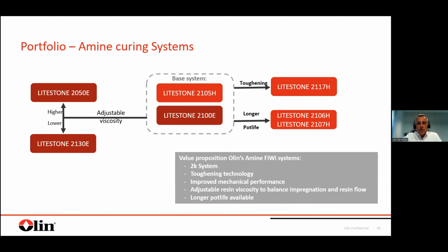For the amine, our portfolio looks similar. Again, we have kind of a base system, which is always a good starting point if somebody starts working on filament winding. Then we have a hardener, which is, again, implementing the toughening technology. We have two different hardeners, which are adjusting the reactivity, so the ability to adjust the formulation towards longer pot life. And in essence, these two hardeners can be processed from an open bath, almost similar to anhydrides. Not exactly with the same latency, but almost similar. And again, we have two different resins to move either to higher or to lower viscosity.